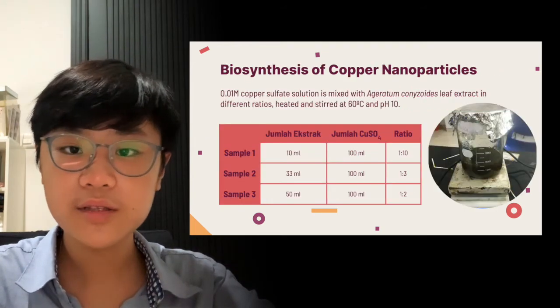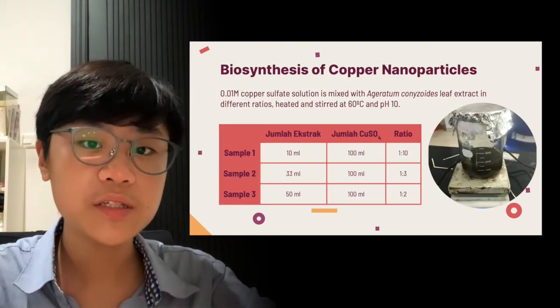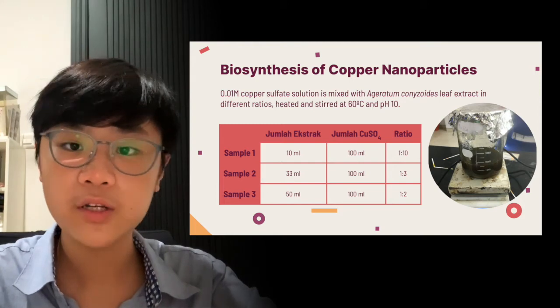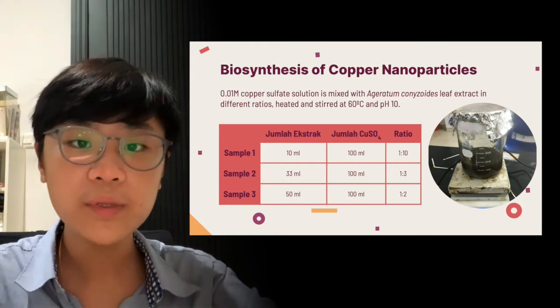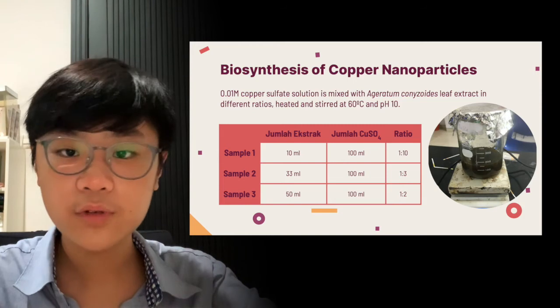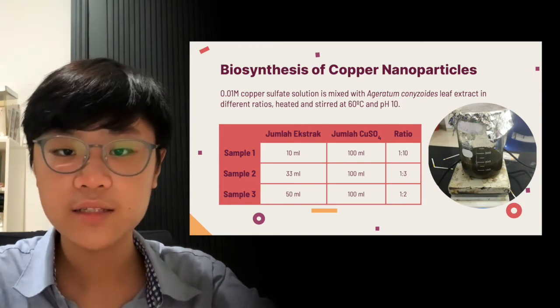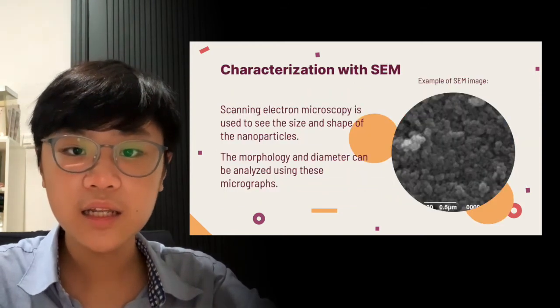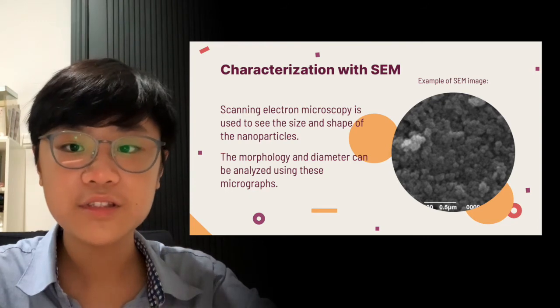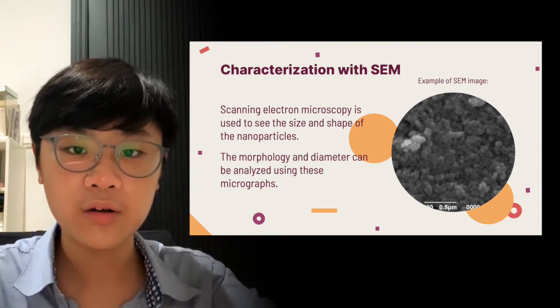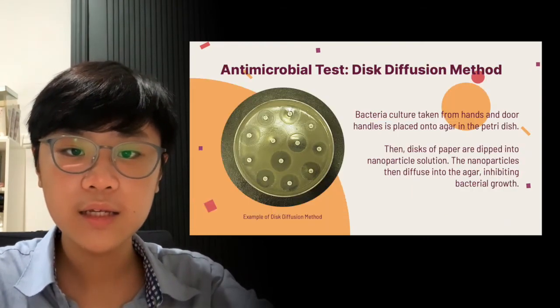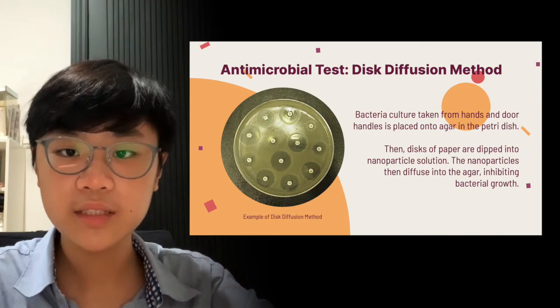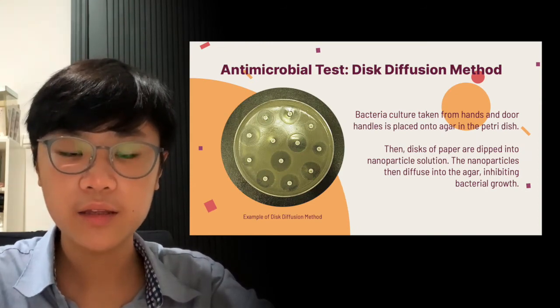In the actual biosynthesis process, copper sulfate solution is mixed with the extract in the different ratios, as I said before, while being stirred and heated. This creates 3 different samples that can be analyzed. Scanning electron microscopy is used to see the size and shape of the nanoparticles. Next, we have the antimicrobial test using the disc diffusion method.